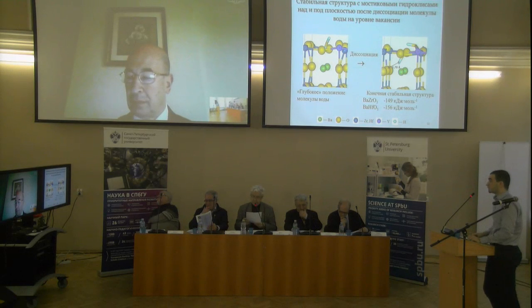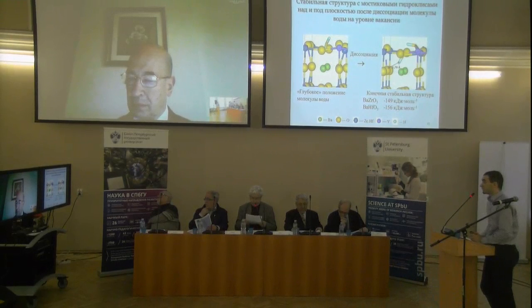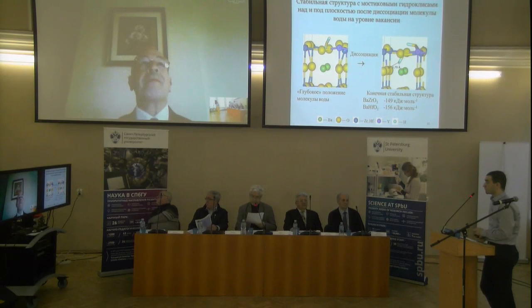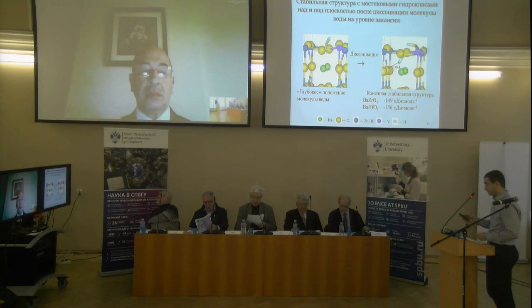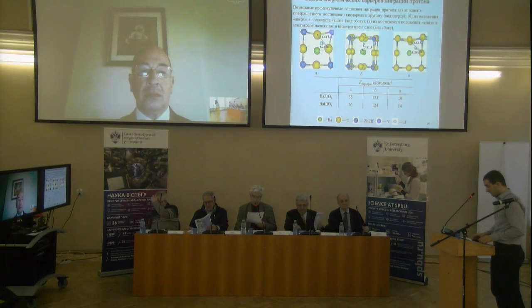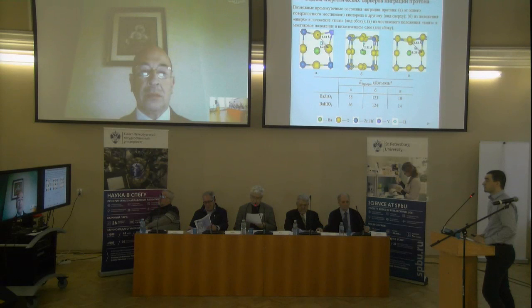On the Y-substituted surface, the water molecule is adsorbed at the place of the oxygen vacancy. Different initial locations of the water molecule over the substituted surface of BaZrO3 and BaHfO3 were considered: one, over the zirconium and Hf atom, two, above the Y atom, and three, above the oxygen vacancy. In all the cases considered, the water molecule dissociates to form two bridged hydroxyl groups.